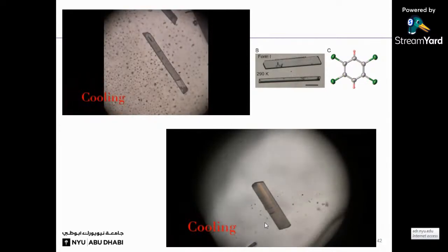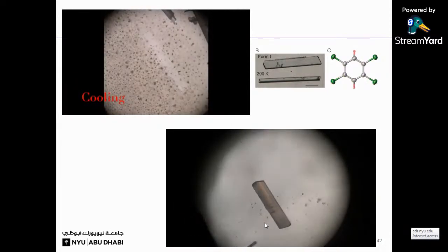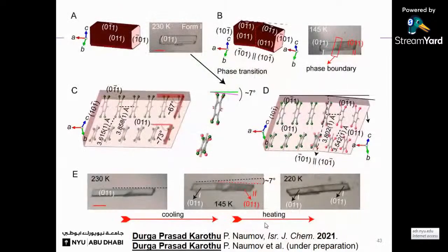When you restrain the jumping, you can see vivid changes in the colors. These are reversible. You can do several cycles. And also I have explained the mechanism by using single crystal X-ray diffraction. In this case, the molecules actually move from one form to another form. There is a slight change in the tilting angles. Other than that, we don't see much changes in these forms.